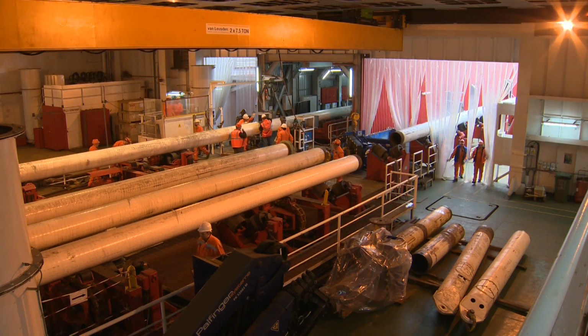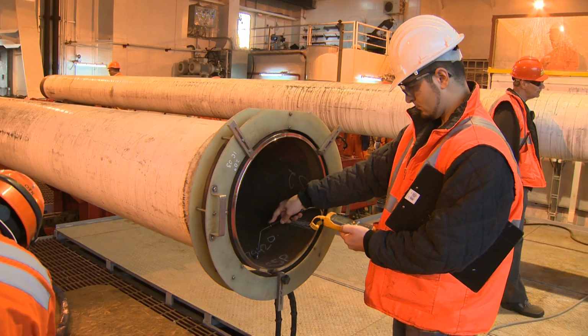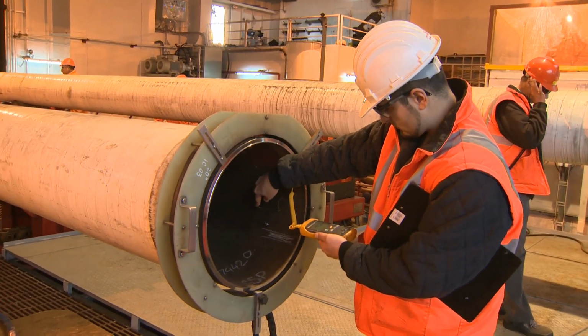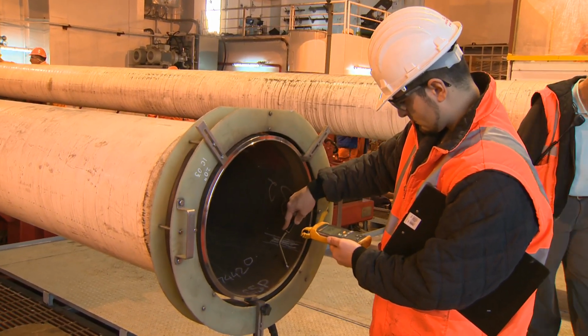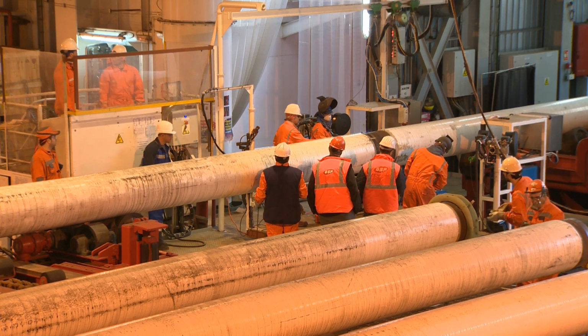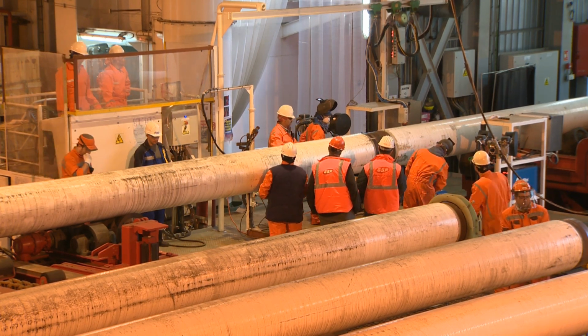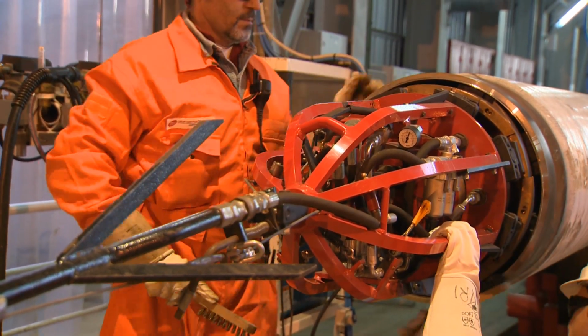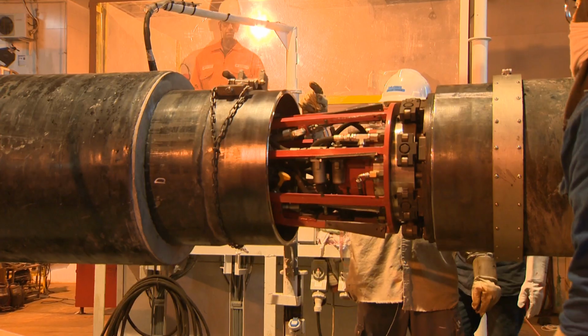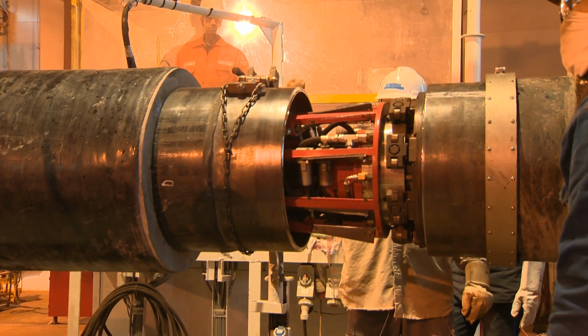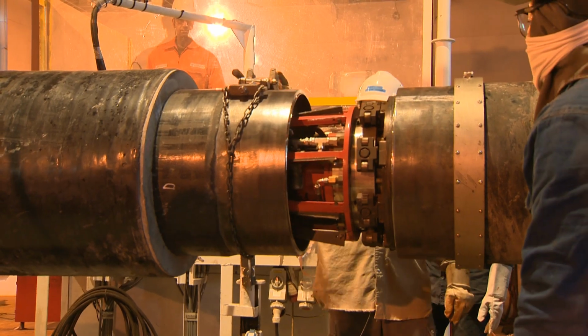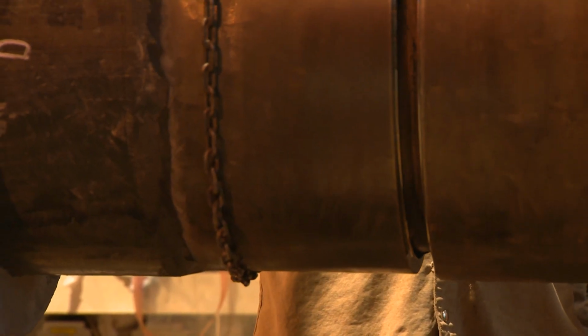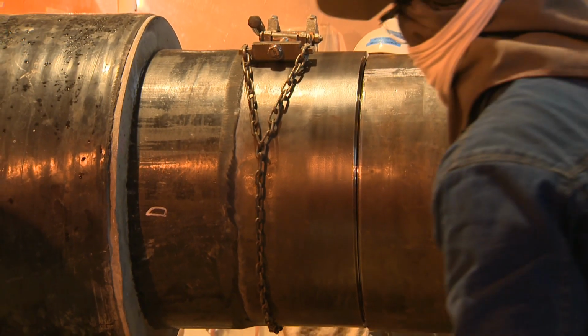2 passes. In order to ensure the welding quality, they preheat the pipe to 150 degrees centigrade using an induction coil. After its completion, the pipe sections enter the fabrication process. The correct welding operation has a number of compulsory stages. The pipe sections are aligned with support of the pneumatic device, which ensures all of the dimensions and alignment requests are observed according to procedures.